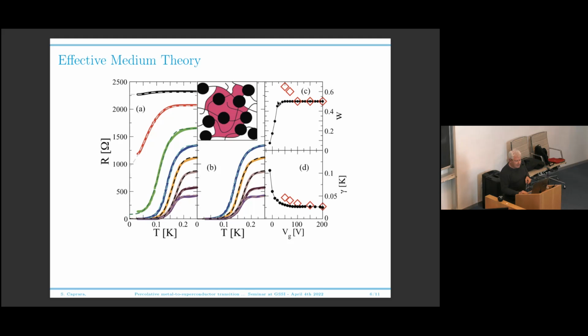As you see, the points give for the weight of the superconducting cluster exactly the percolation value 1/2. Why? Because we are assuming that disorder is homogeneous, and then we are forcing our cluster to be exactly close to the percolation threshold to produce these long tails in the resistance curves. Of course, if you abandon this assumption that disorder is homogeneous in your system, then you get a much more reasonable solution where your superconducting fraction may not really be at the percolation threshold, but of course you can no longer use effective medium theory to solve. You have to go to the exact solution of Ohm's law and Kirchhoff's laws in a random resistor network.